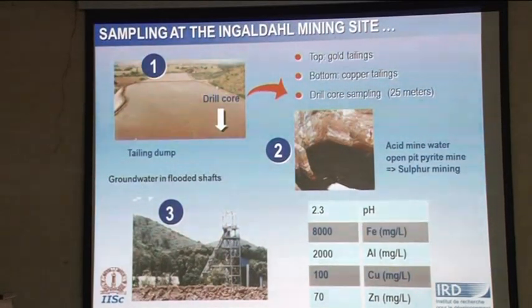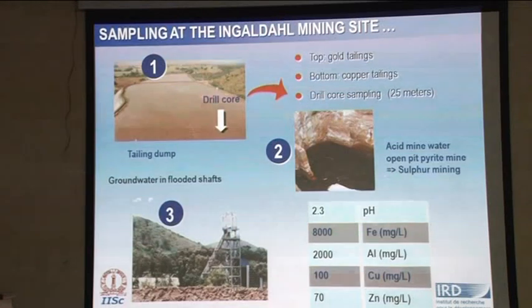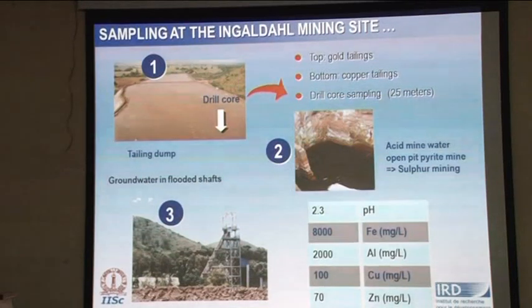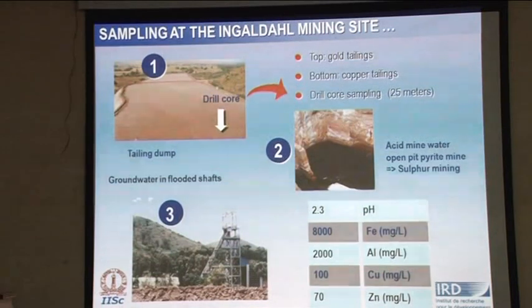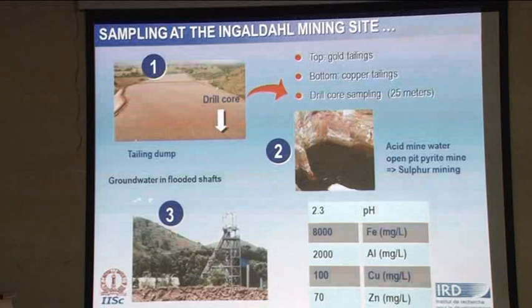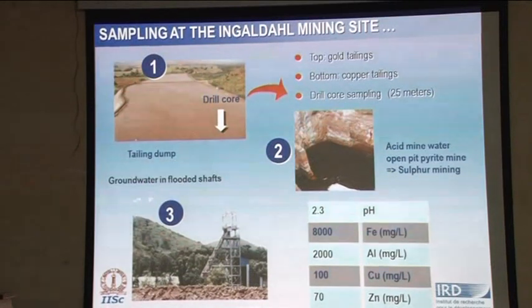And what you see here, which is there even today, is a small sort of well where you can see that the pH of the water is close to 2. And this is due to the oxidation of pyrite. During the time of the British era, they were wanting to produce sulfur from this pyrite deposit, and they did some workings, but later it was not commercially feasible. But even today, when you go there, you will see that the water is highly acidic here. Its pH is of the order of 2 to 2.3.